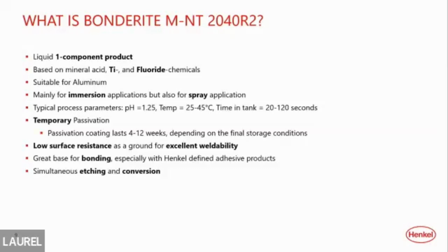The temporary passivation coating is good for 4 to 12 weeks, depending on final storage conditions. You cannot store this right next to your tank. It needs to be clean, dry, covered, and low humidity. We do have one supplier that has it really dialed in, and they can store it for 6 months. But I do not tell people that they can do it for 6 months, because they even have specialized packaging that they put everything in and then they store it.